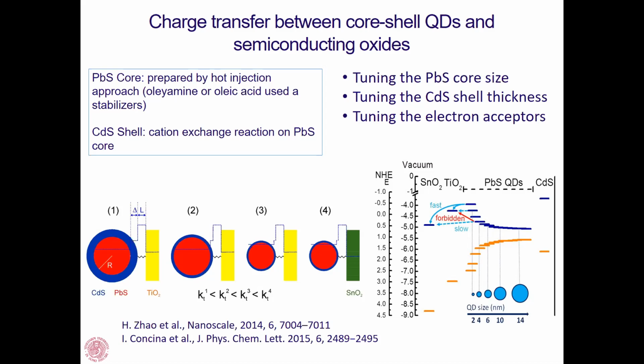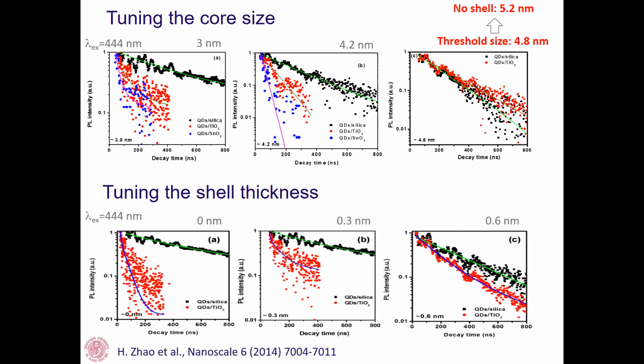So you want to be able to avoid this kind of process, whereas in solar cells you want electrons to be transferred. In this case, you do not want the electrons to be transferred; you want radiative emission. By applying photoluminescence lifetime measurements, in dark you see the crystals embedded in silica spheres, so in a material which is not transferring electrons. You see that by increasing the size of your crystal, you increase the lifetime of the photoluminescence, reaching a threshold of 4.8 nanometers. The same results hold for silica, saying that at that point, your nanocrystal is no longer injecting electrons into the